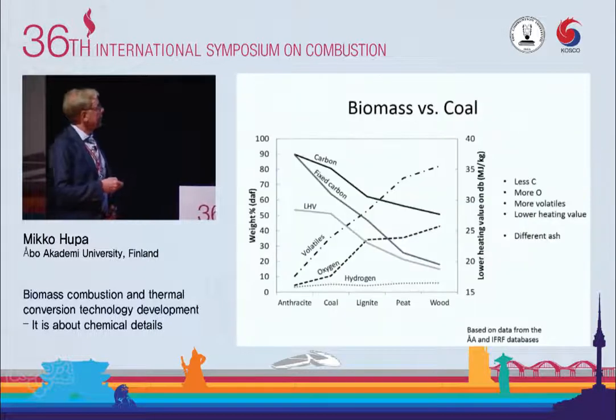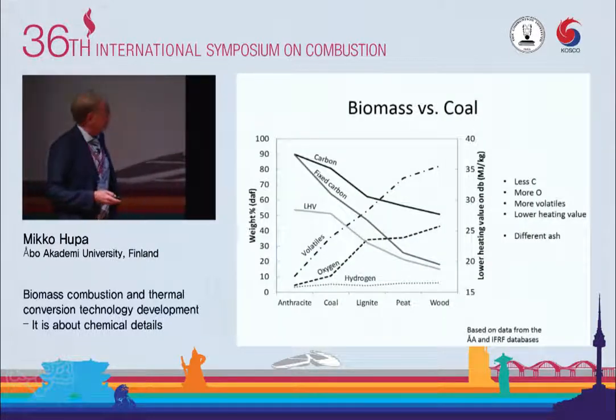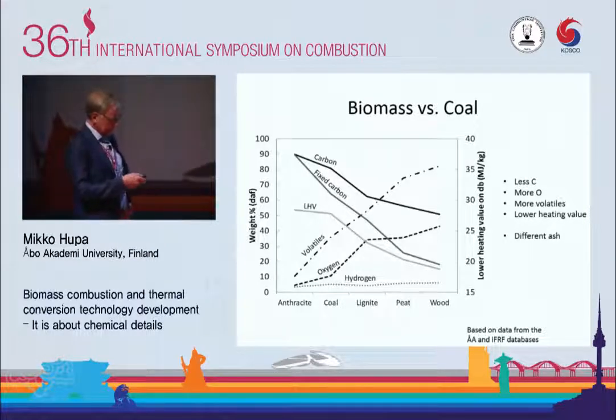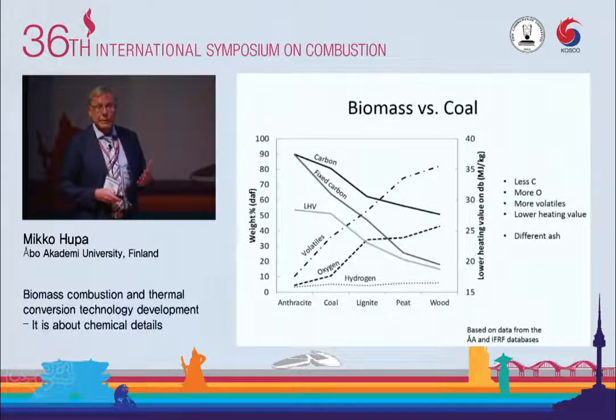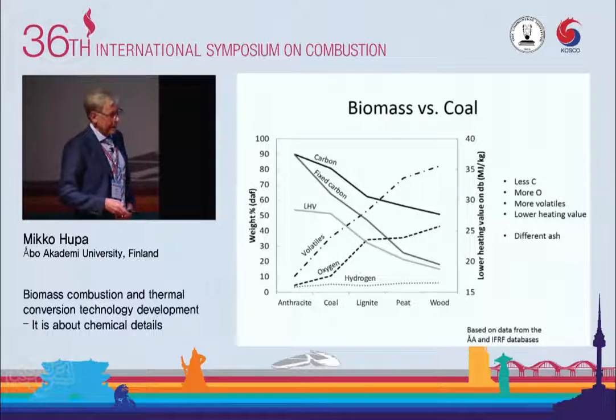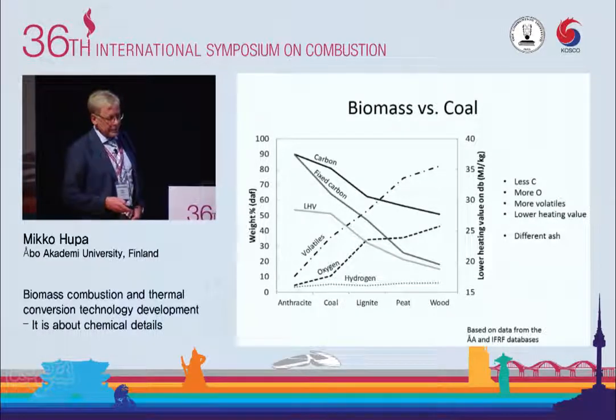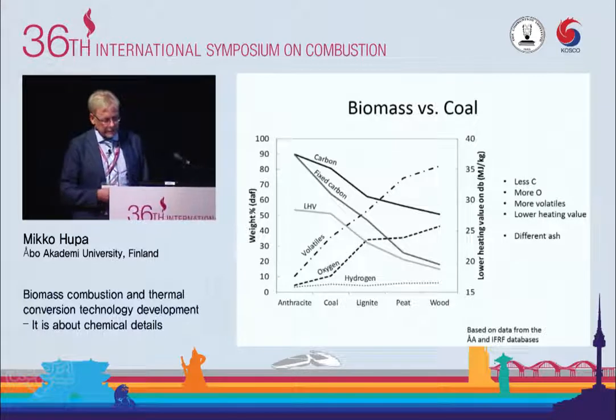And I have another picture showing also the same relationship. Here you see starting from anthracite, the volatiles content goes steeply up, and in fact for most wood qualities or biomass qualities we speak about 80+% volatiles and 20% fixed carbon. The lower heating value in the same way goes down, so they have a low heating value, but on the other hand, as I mentioned, some of them are quite available and inexpensive.